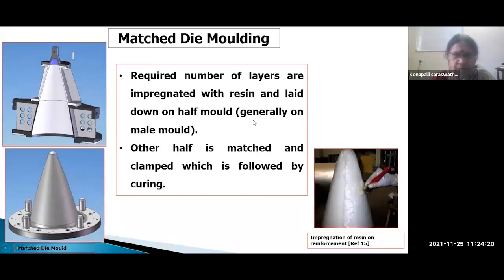Then this is the match die molding. In match die molding, die and punch, the male-female parts of the mold are matched with fasteners, and the required number of layers are impregnated with resin and laid down on half the mold. Generally, in this mold we make the layup, and the other half is matched to this and clamped, which is followed by curing. So no vacuum bag and all is required for this, unlike the autoclave process.